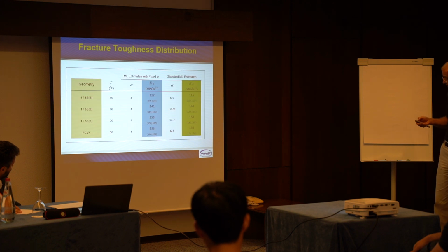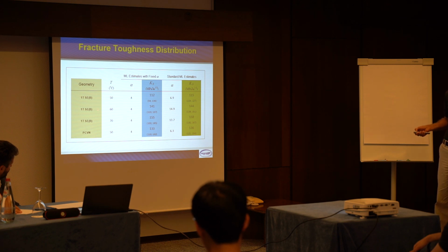It's not like an impact load. You see here almost no scatter. Nevertheless, we still fit the distribution, a Weibull distribution, just following the standard. So the question remains: what would happen if, instead of using the maximum likelihood estimate of the Weibull parameters, we used the standard, which has a fixed value of 4? There are reasons for fixing this value as 4.